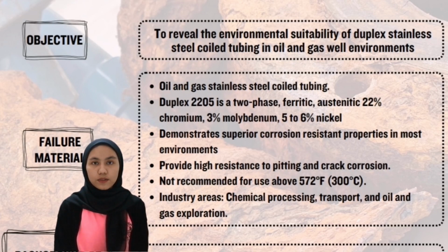The failure material used in this investigation is the duplex 2205 stainless steel, which is a two-phase structure consisting of 50% austenite and 50% ferrite, and it also consists of 22% chromium, 3% molybdenum, and 5 to 6% nickel. As we can see, it has the highest percentage of chromium, which is 22%, and due to this high percentage of chromium, it demonstrates superior corrosion-resistant properties in most environments. Other than that, it also provides high resistance to pitting and crevice corrosion.